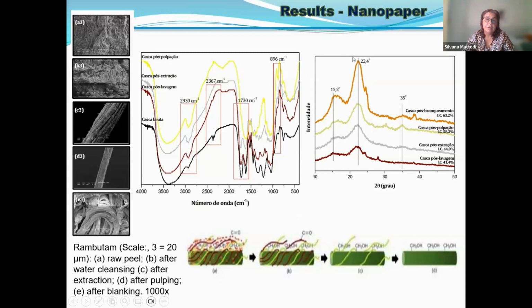Higher this angle, higher the crystallinity. So if the peel after just cleaning has a lower peak, lower intensity of this peak, after extraction it's a bit more, after pulping a bit more, and after bleaching higher. What is really occurring in the fiber is that you are cleaning the fiber. So the pre-treatment is cleaning the fiber.